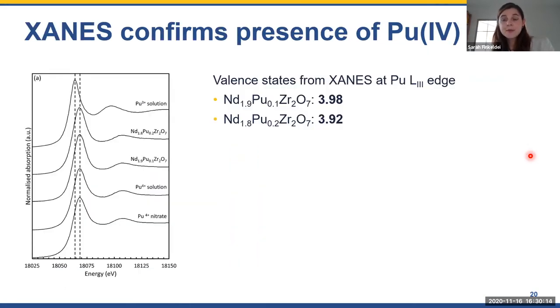So those experiments were performed at the ANKA synchrotron facility in Karlsruhe in Germany, and with X-ray absorption near edge structure, what we were able to do is to look at the oxidation state of plutonium in those ceramics. And you can see here the XANES spectra, and this is a plutonium 4+ nitrate, which was my starting material. I have another plutonium 4+ solution as reference and a plutonium 3+ solution. And these are the two plutonium pyrochlores I fabricated, the one with 5 and 10 mole percent plutonium. And what you can see here is that the absorption edge of these two plutonium pyrochlores is in accordance with the plutonium 4+ solution and standard.